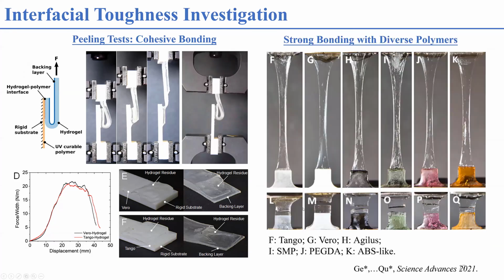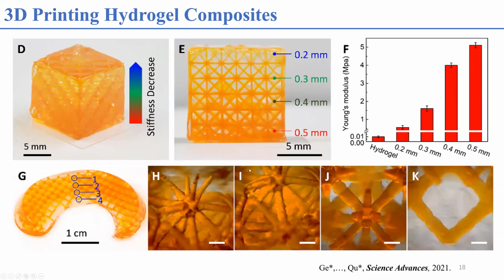And also our method shows very good generality. We can print our hydrogel with a lot of different polymers, such as Tango, Vero, soft material, rigid material, even ABS material or shape memory polymer or PEGDA. All of these, we can print the hydrogel with, okay. And then we show a few applications. For example, we can print a lattice structure reinforced hydrogel composite. So we can print a hydrogel where we have a rigid lattice structure to reinforce it.